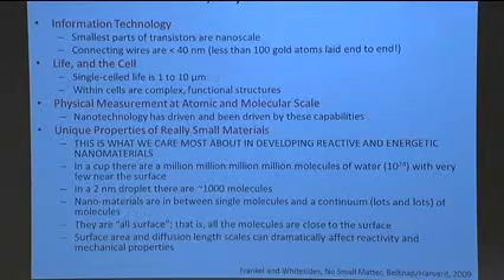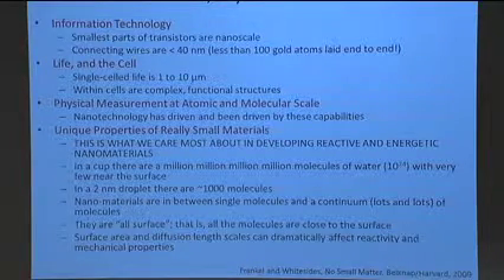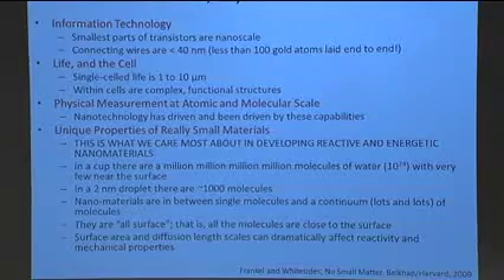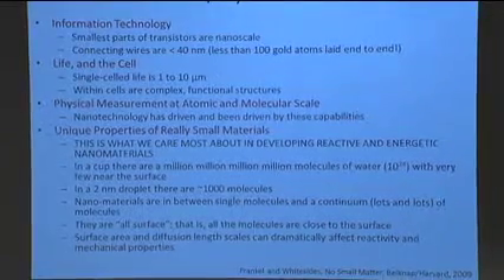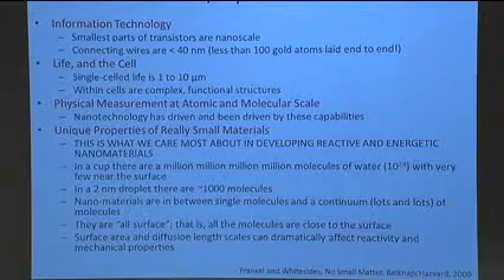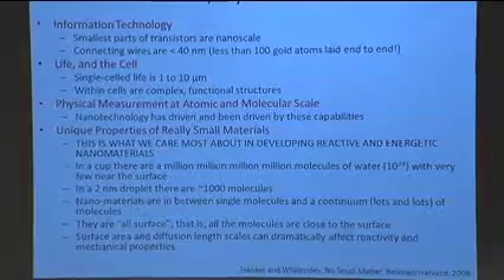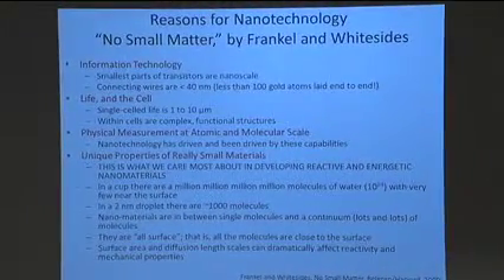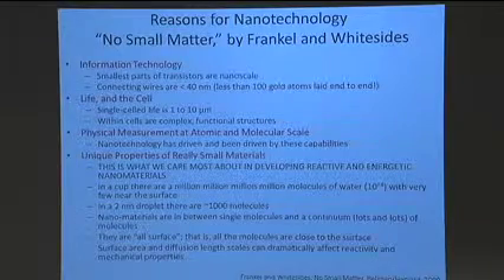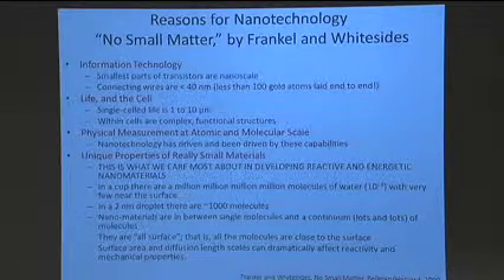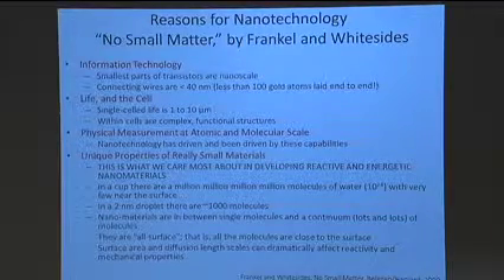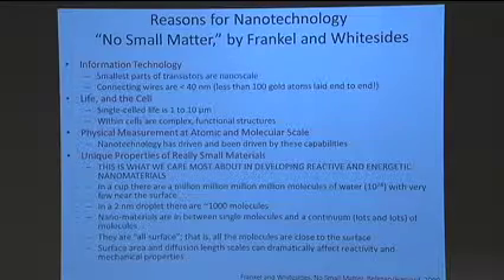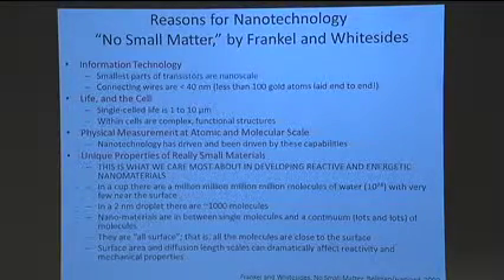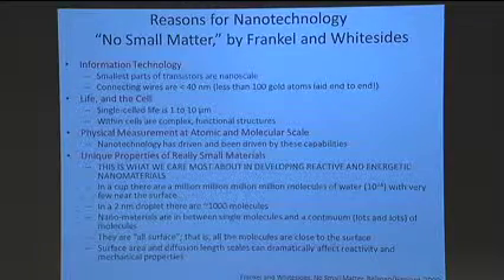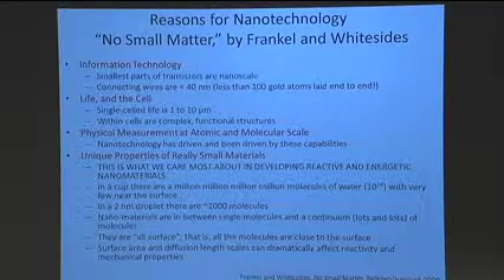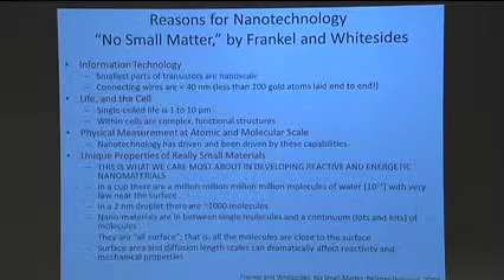As one starts looking, the first area in which George Whitesides looks is microelectronics. If we look at microelectronics, we're looking at essentially computers and the use of nanoscale material. If you look at these systems, you can see that today transistors, if you look at their internal structure, have a significant amount of nanoscale structure. The connecting wires, for example, are less than 40 nanometers in dimension. This is equivalent to having 100 gold atoms end to end, so very small features. And it's quite amazing that we can even build these devices, let alone mass produce them in the quantity that we do. The second area he brings out is essentially microbiology.